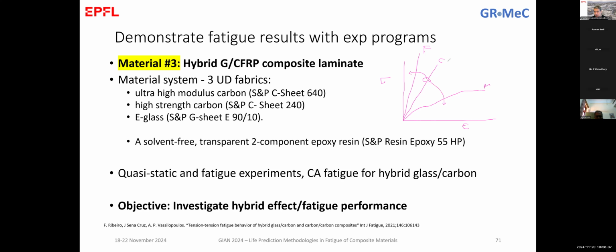The properties of this composite can be defined by the rule of mixtures. The rule of mixtures says that the properties depend on the percentage of these two materials. So the hybrid effect is an effect that we have in certain configurations of materials, where the properties of the composite that we are building sometimes override, become to the left, so become better. The mix of two materials becomes better than the best one of the materials used for the analysis.